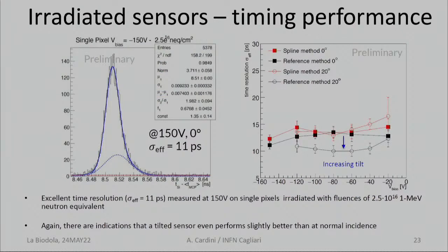For what concerns the time resolution, for the irradiated sensor at 2.5 times 10 to the 16, we have an effective time resolution of the order of 11 picoseconds. This is a very excellent time resolution for a detector irradiated to such high fluences, and we still see the effect of increasing tilt improving the time resolution.